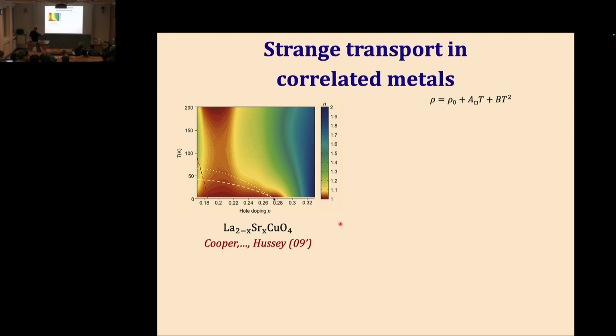So the end of the superconducting dome is right here. There's a superconductor to metal transition, and at a slightly higher doping, this red color also starts to cross over towards blue, which is exponent 2, which is Fermi liquid behavior. So we believe that far enough out in doping, the system crosses over eventually to being a more or less conventional Fermi liquid. But in the same place where the zero field ground state is a superconductor, the normal state is this strange metal with linear resistivity.